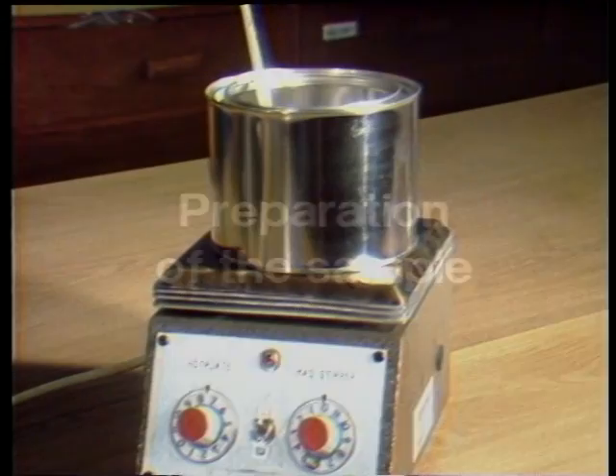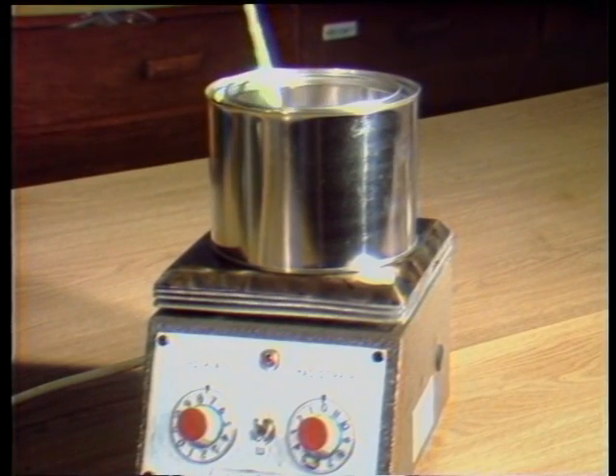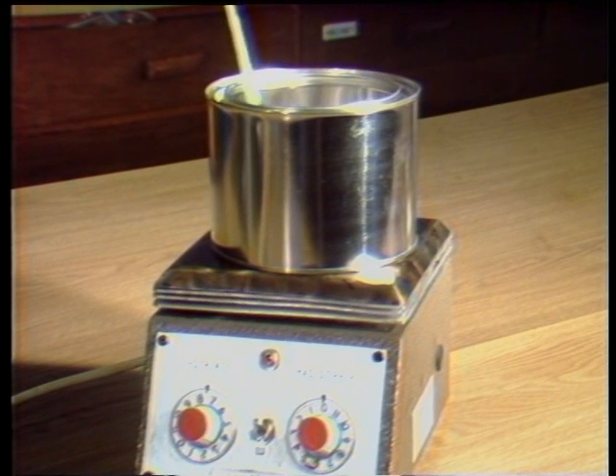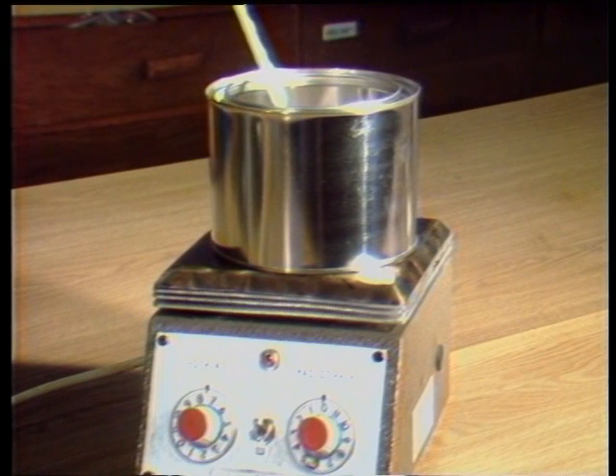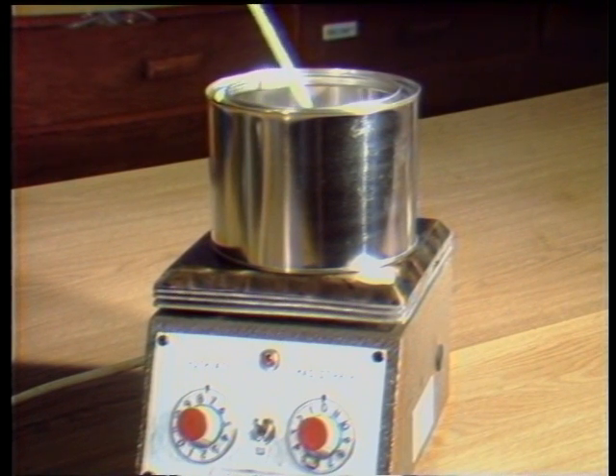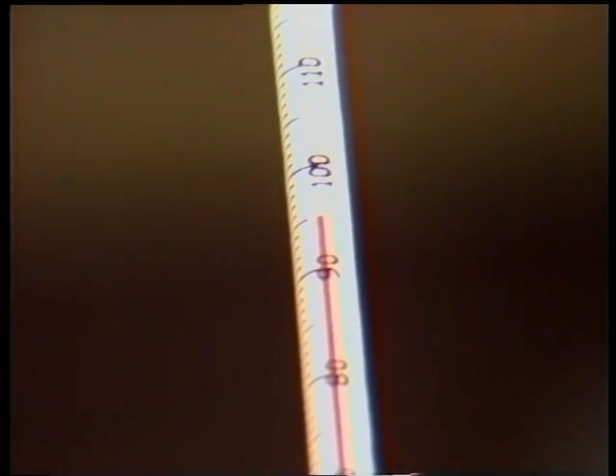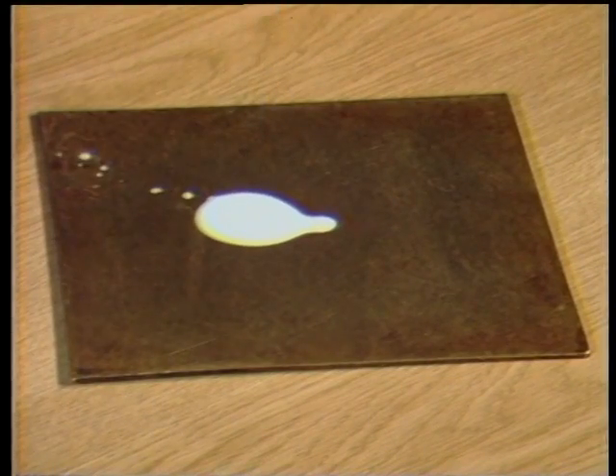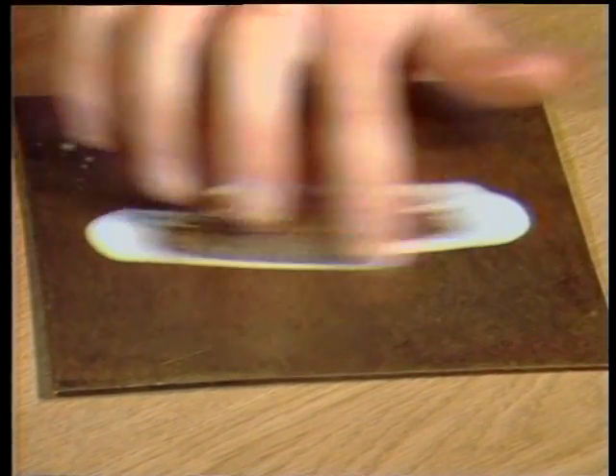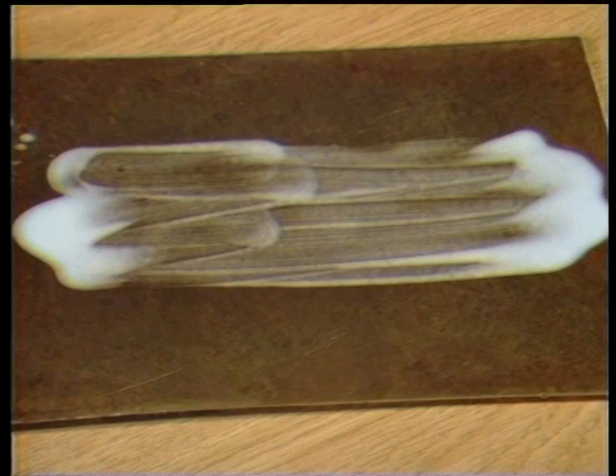Preparation of the sample. Heat the field sample in an oven or on a hot plate with great care to prevent local overheating until it's become sufficiently fluid to pour. In no case should the temperature be raised to more than 90 degrees Celsius above the expected softening point of the bitumen. Lightly coat the upper surface of the small metal plate with the glycerine talcum mixture to prevent the bitumen from sticking.